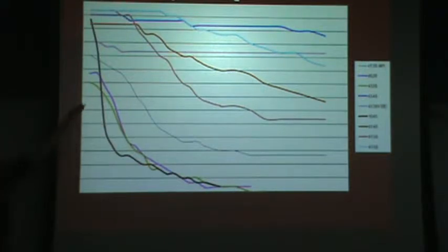But when we get to carbon over, say, about 0.6, the hardness at J1 doesn't really get any higher. So that is to say, if I had a 1080 or a 1090 or a 52100, and I quench them doing a Jominy test, and I do a hardness check at J1, they're all going to be about the same.